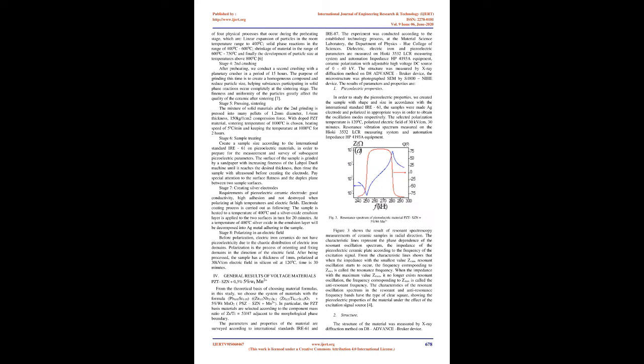According to the DTA-TG diagram, there are two peaks absorbing heat and the weight loss at 370°C and 900°C with analytical sample volume of only 50.63 mg. Experiments show that the fabricated samples with large volume need to investigate higher burning temperature. In this technological process, the first burning temperature was selected at 650°C, 700°C and 750°C, selecting sintering temperature at 950°C, 1000°C and 1050°C. The result: choosing the first calcination temperature at 700°C and the sintering temperature at 1000°C is the best. This is the basis for selecting the burning temperature for second times in the process of synthesizing hard piezoelectric materials system PZTSZ doped Mn4+. Figure 2 shows Differential Thermal Analysis Scheme DTATG.